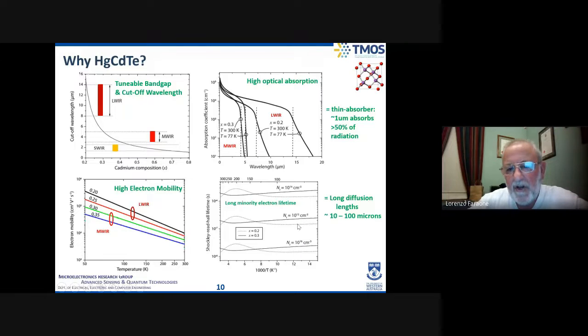And if you look at the lifetime, high quality material typically has a lifetime around a microsecond or so. So if you remember the equation for D star, we have the absorption coefficient, which in this case is high, the electron mobility, and the lifetime.